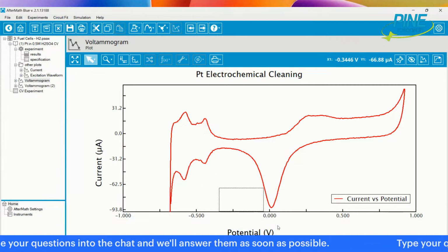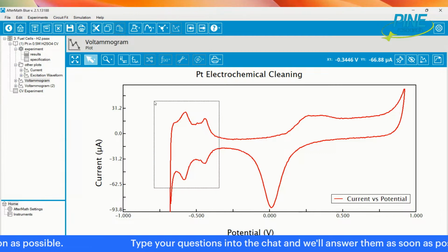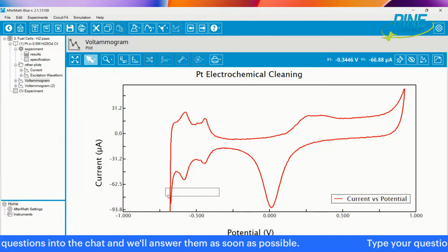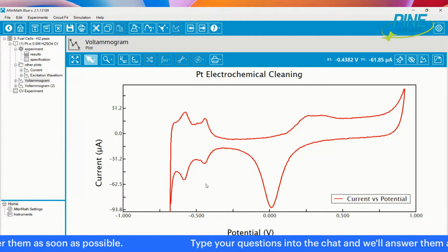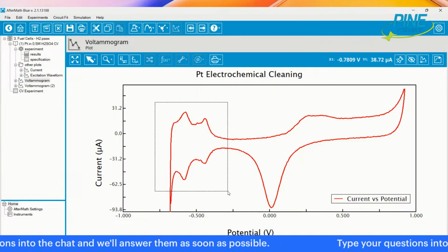The region close to 0, now this is shifted because of the reference electrode used, but the most negative region, if you will, is the platinum hydrogen adsorption-desorption region. Also, as you go further negative, it's the hydrogen evolution reaction or the hydrogen oxidation reaction, depending on which direction you're going. But basically, this part of the curve is where you're adsorbing and then desorbing hydrogen on platinum.